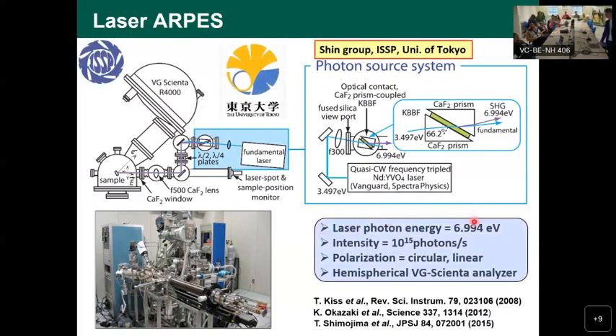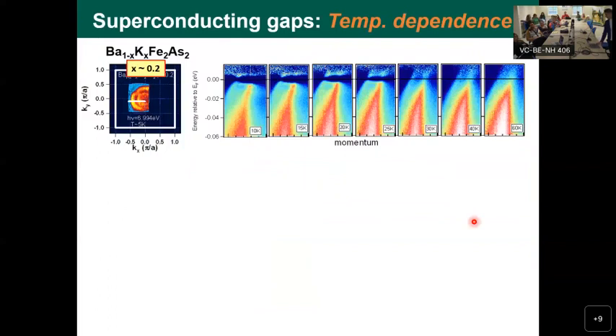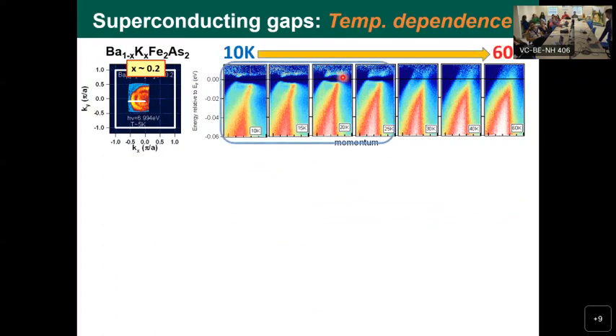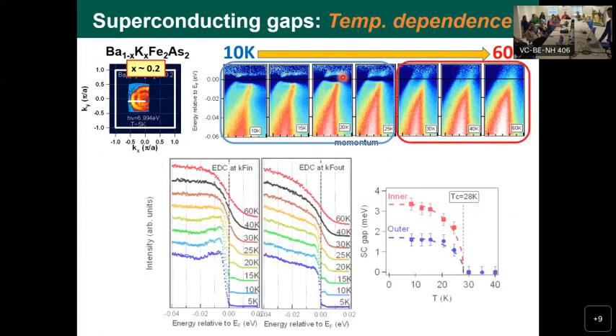And this is very low energy, 7 eV. It has many advantages over synchrotron radiation. And here is an example of how we can see the superconducting gap. Of course, I will not go deep into the details, but just to show you, the lack of intensity here means the opening of the gap. This continues all the way below TC, as long as the material is in the superconducting state. When it goes to the normal state, there is no more superconducting gap. Usually people plot this gap versus temperature, and it shows behavior similar to BCS, but with some differences in the pairing strength and so on.